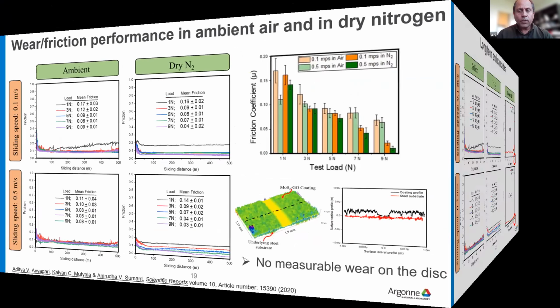And if you look at the wear on the disc, the red is basically where you actually remove the coating. So we basically don't see any measurable wear even after this test. So this is very interesting: just a couple of microns thick, this spray coated surface is functioning very, very well, at very high contact pressure up to 1 gigapascal.